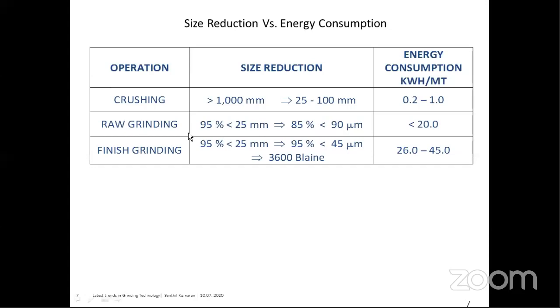When we see this raw grinding, from 25 mm we are reducing to 85 percent passing 90 micron. And for the finish grinding, 95 percent passing 45 micron. So it is an ultra fine product. Cement, as we all know, is a very ultra fine product. That's why the power consumption is on the higher side.